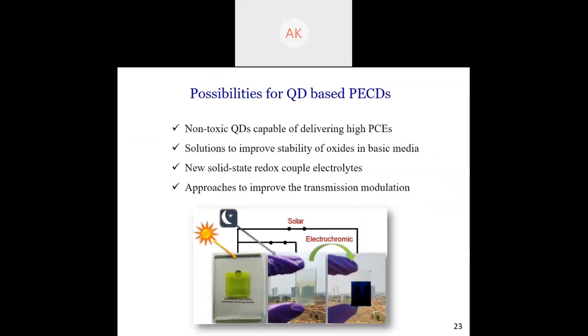And there have to be approaches to improve the transmission modulation. Now, improving the transmission modulation cannot hamper the high power conversion efficiency. An ideal PECD, we remember, has to have high power conversion efficiency as well as good optical contrast. So if you see the two photographs that were clicked by me, you can see the color. It is transparent and it also has the IITH building behind it. And when you have a solar connection, you also get efficiency. When you have electrochromic, you can also test single film electrochromic and also a PECD electrochromic, whichever is convenient.